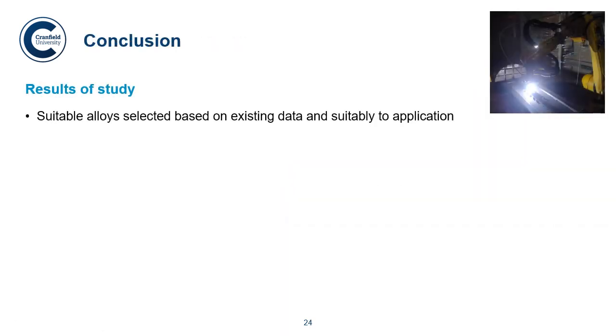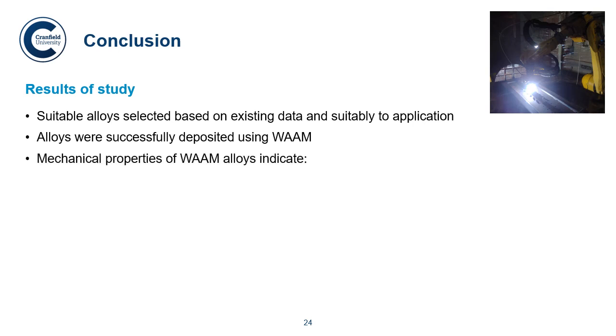So in conclusion, we had the following results of the study. We selected alloys based on the existing data and the suitability to the application. All the alloys were successfully deposited using the WAAM system. And the mechanical testing indicates that there was a correlation between the two precipitation hardened alloys, which were 718 and René 41, and there wasn't much of a correlation between those two and Haynes 188, which was the solution strengthened alloy.